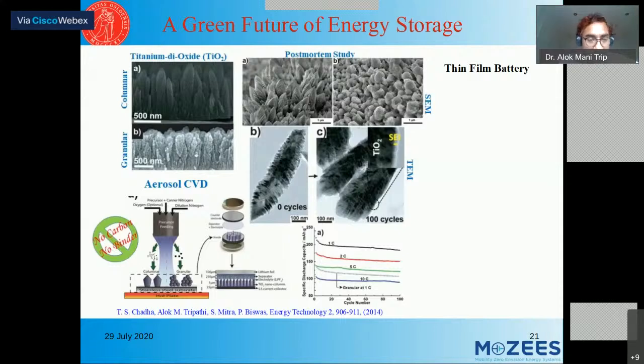Here what we showed is that you can make the battery without using any kind of carbon. Generally a battery electrode has three components. One is your active material, which reacts with the lithium. Another is your carbon, which conducts the electrons. And the third is the binder, which is used to make the film. Without using any binder or carbon, you just deposit nanocrystalline titanium oxide on the current collector, simply like in this cell setup.